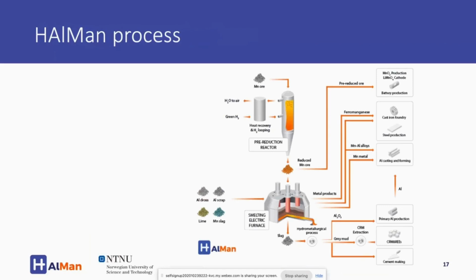And from this process, we get out two products. We have the metal or the alloy and the slag. And both are seen as valuable products in this project. From the alloy coming out, we have demonstrated with the steel foundry how to make low carbon ferromanganese steels. This we can do because we don't put in any carbon in the process, which means that we have less carbon in the product, which is a high value product for the steel industry. And we also evaluate the use of this ferromanganese or the manganese aluminium alloys in the aluminium industry and see if they can use this product as well in their alloys or in their products.